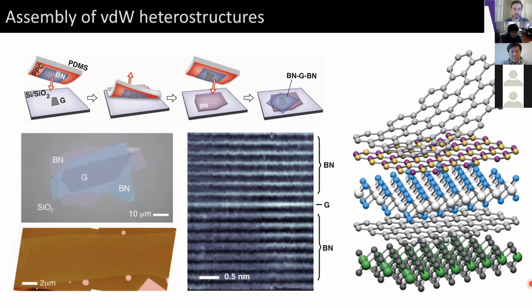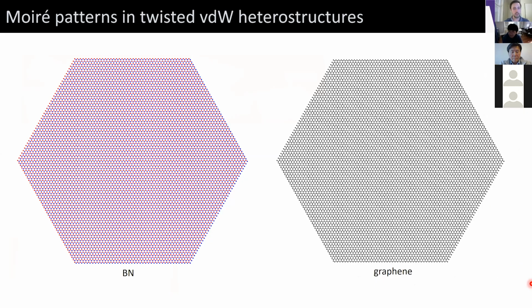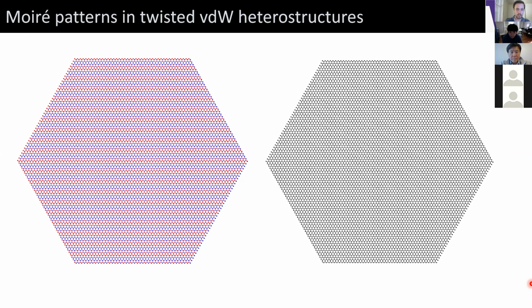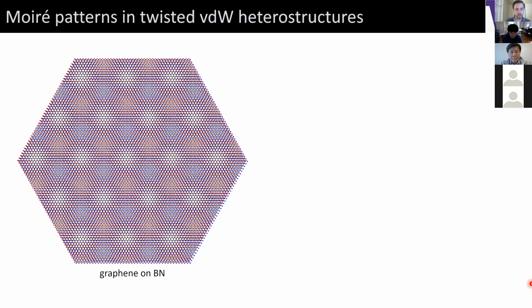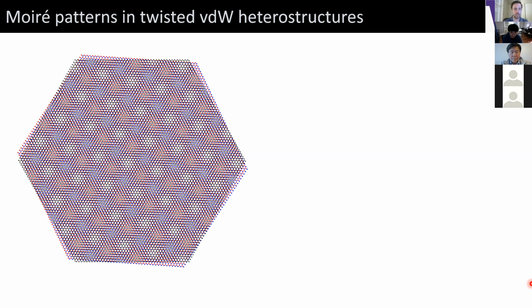Of course, there are other experimental tuning knobs that you have accessible upon stacking different van der Waals materials. So if I just take two hexagonal lattices like graphene and boron nitride and overlay them, the lattice mismatch means that I get this emergent geometric interference pattern called a Moiré pattern. And then if I change the twist angle between these two crystals, I can change the period or the wavelength of this Moiré pattern, which effectively acts like a superlattice for the graphene.